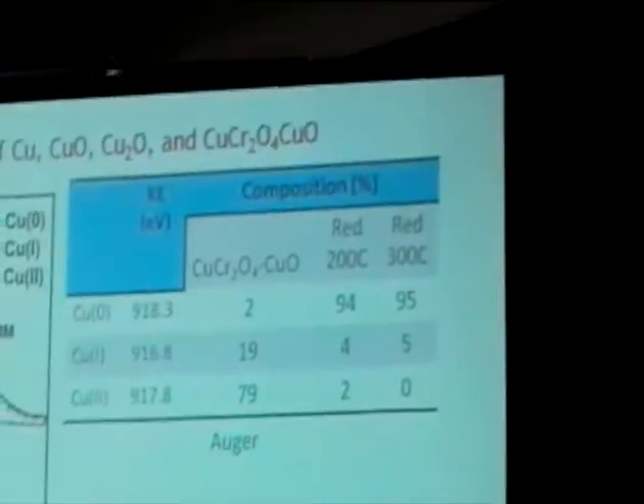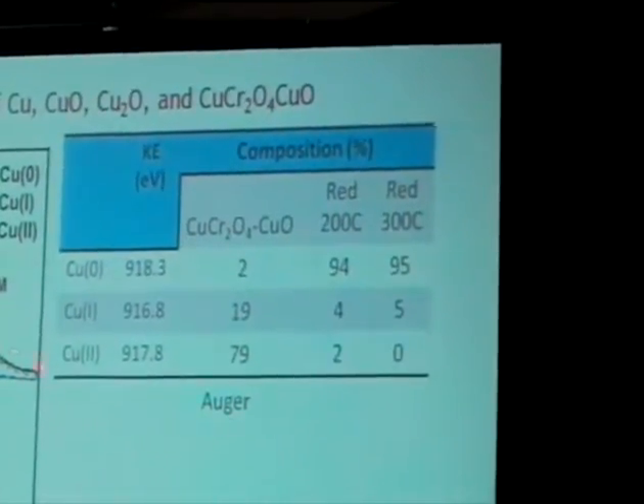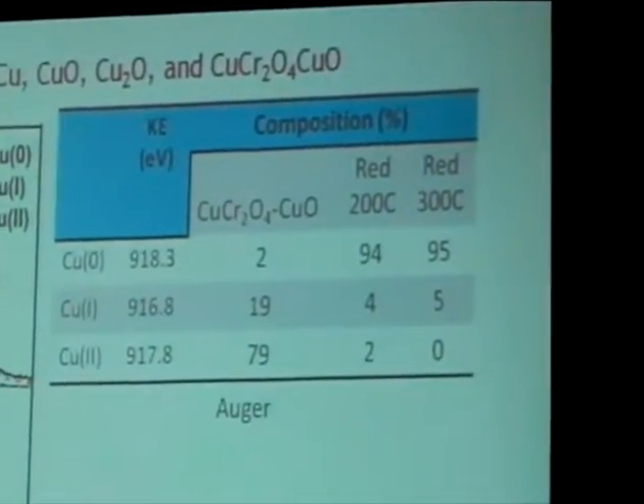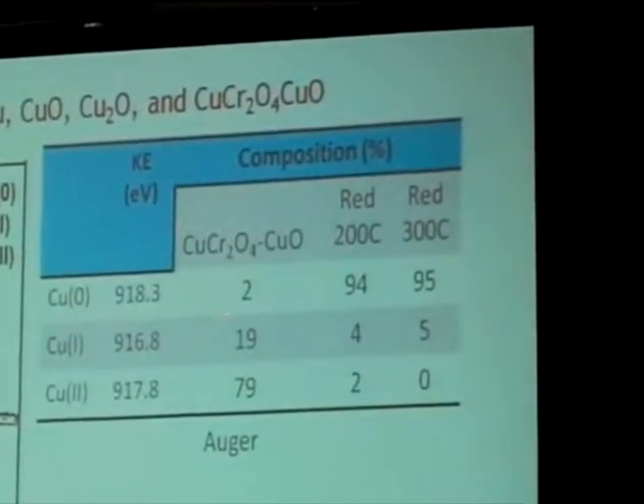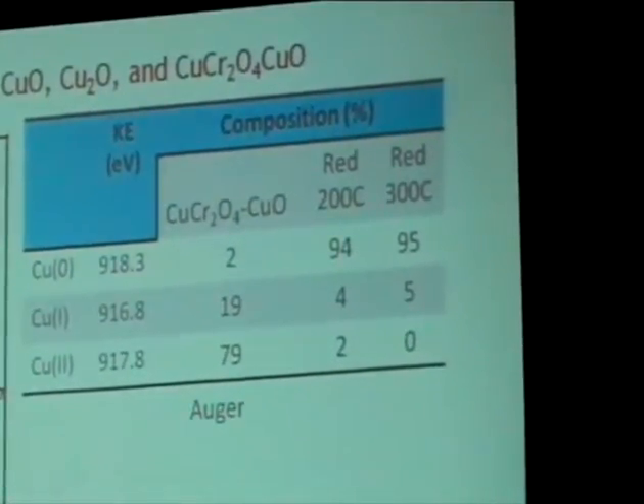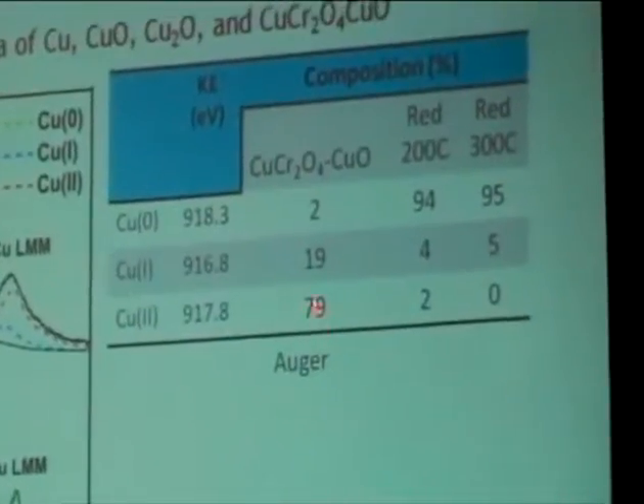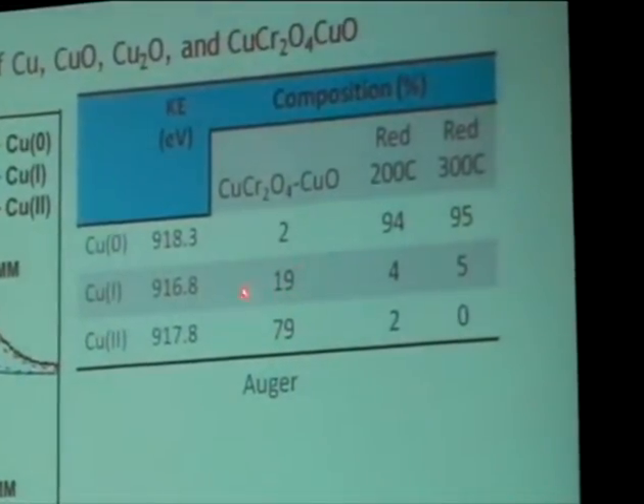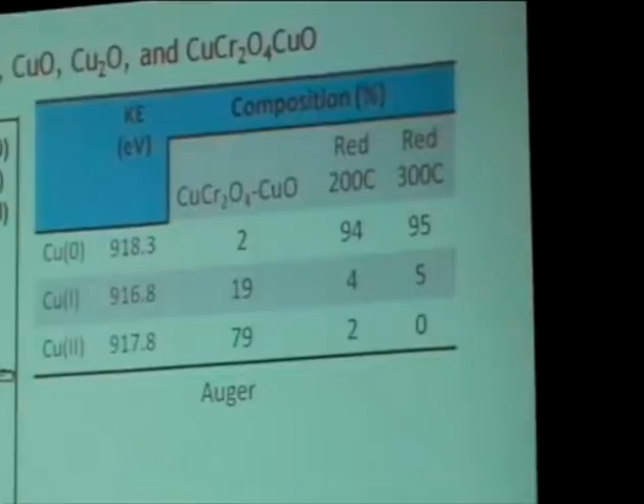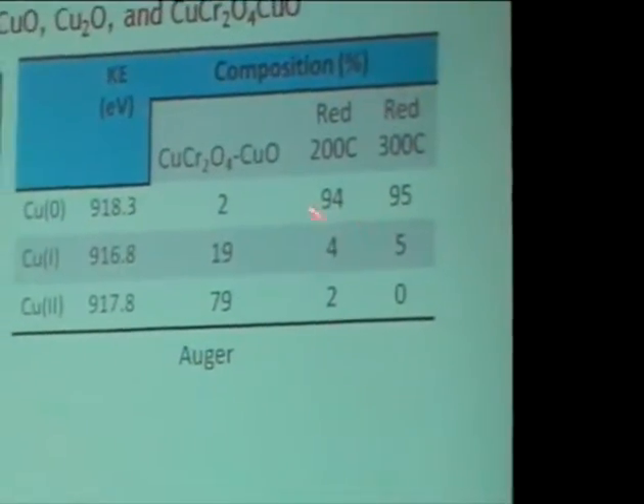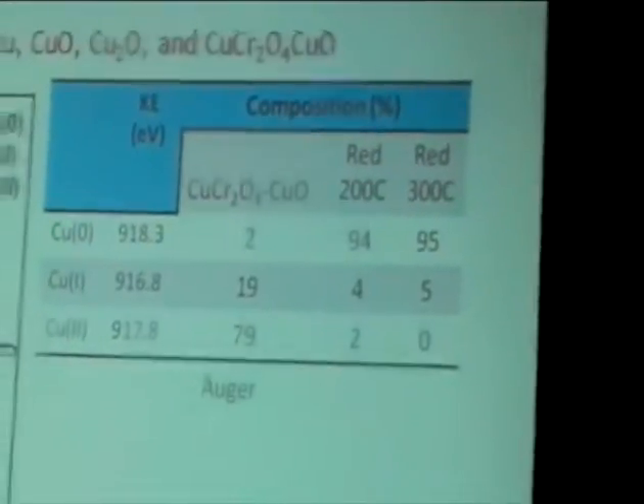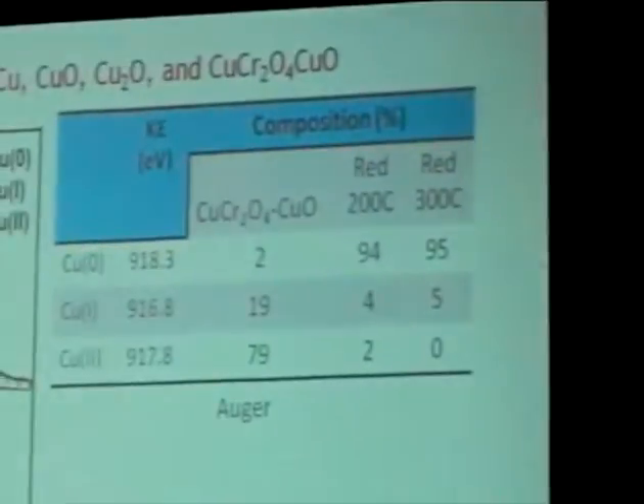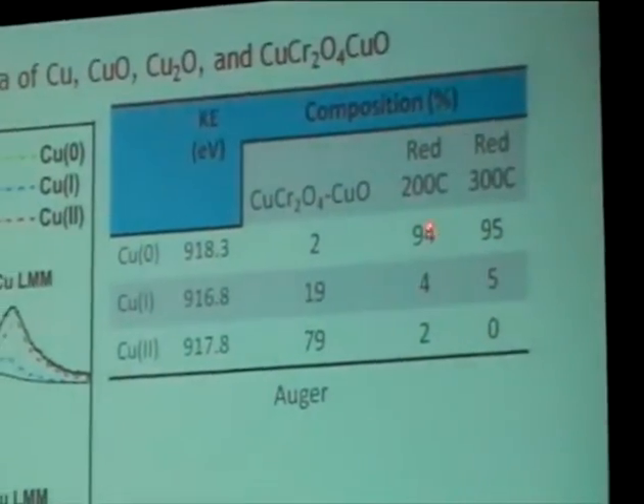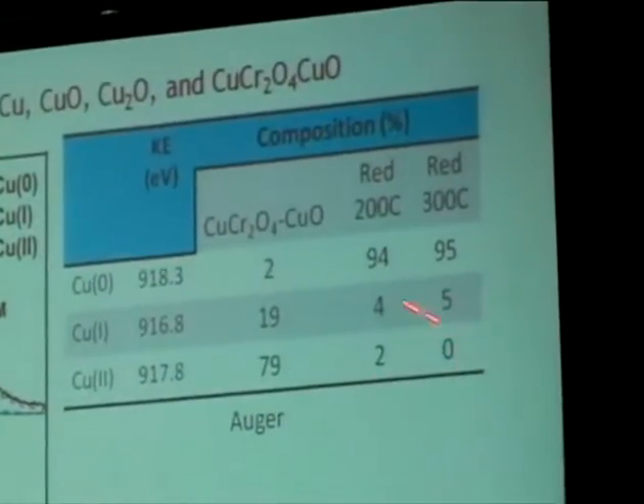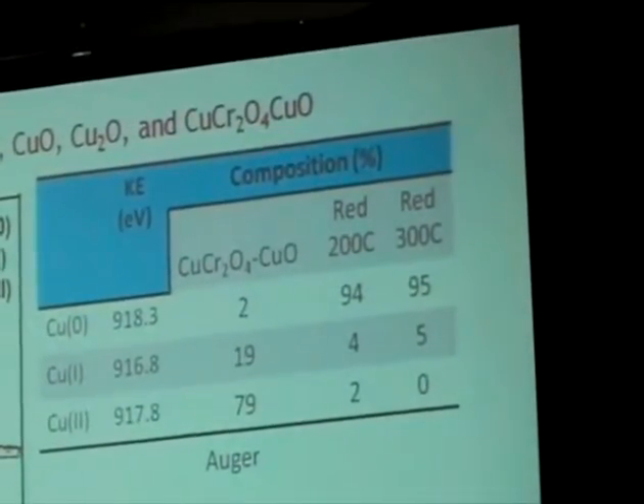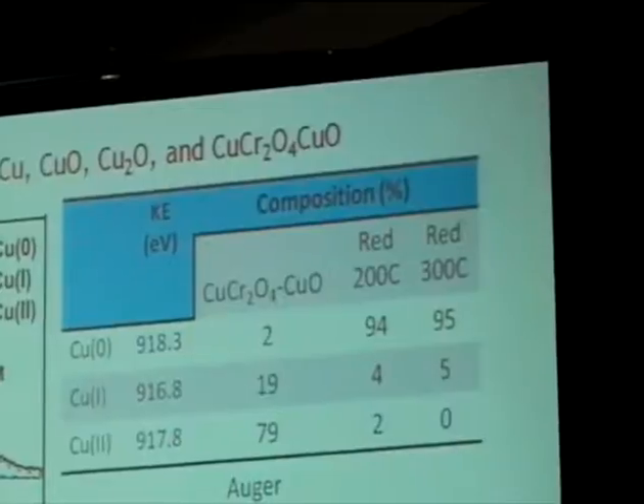If we look at the Auger, which can tell us something about the oxidation state of the catalyst, the initial material, which we received from the manufacturer, is primarily copper 2, okay, with a little bit of copper 1. There's almost no copper 0 from this. When we reduce it at either 200 or 300 degrees, the 200 degrees again being the preferred material, we reduce it completely down to copper 0, and there was almost no copper oxide left for this material.